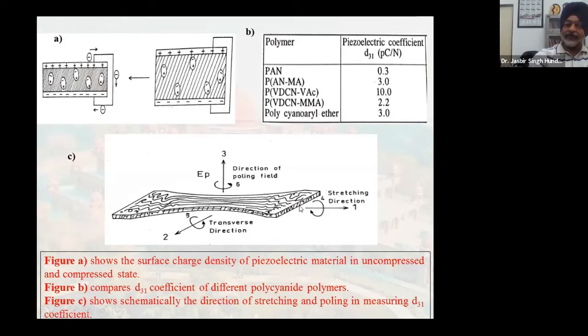And perpendicular to the stretching direction, we have direction 2. So this is direction 1, this is direction 3, and this is direction 2. And if you twist the film, then you may get other axes, like axis 4, axis 5 and 6. But for us, directions 3, 1, and 2 are the ones that are important, right?